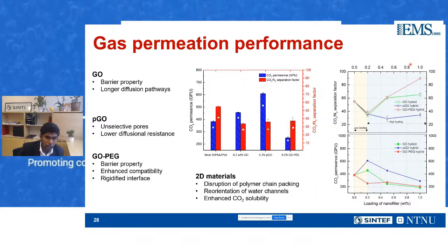And in this system, we also found that only 0.28% of graphene oxide is necessary to disrupt the polymer chains to our benefit. That low loading is mainly because of the two-dimensional structure and the volumetric effect that the graphene oxide has on the disruption of the polymer matrix itself.